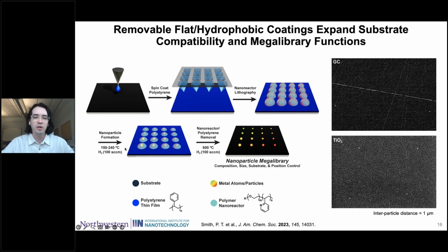And so what we discovered is that we can take an arbitrary substrate, coat it with a polystyrene film, and do all of the lithography and particle formation on that polystyrene film. And then higher temperature treatment will just degrade the polystyrene and deposit the particles on your substrate of interest. And so now we have this universal coating that we can apply to anything and have a much more reliable megalibrary synthesis technique. You can see here on the right, these patterns of gold nanoparticles on a very rough glassy carbon surface, or this nanoparticulate titania surface. So you can get now nanoparticles patterned on top of other nanoparticles.